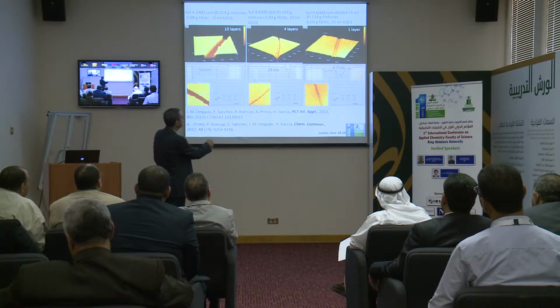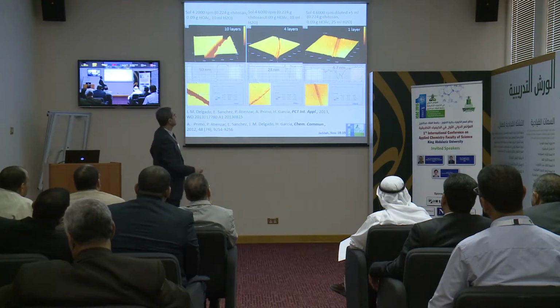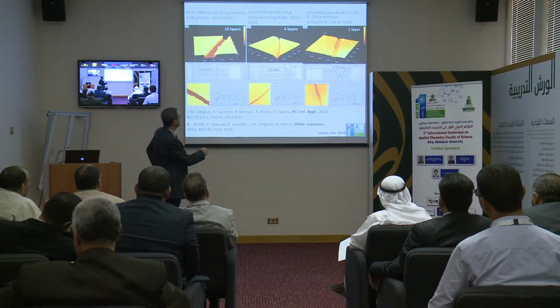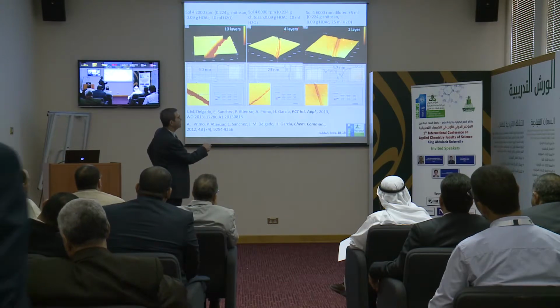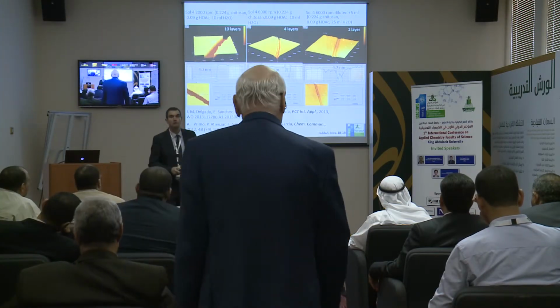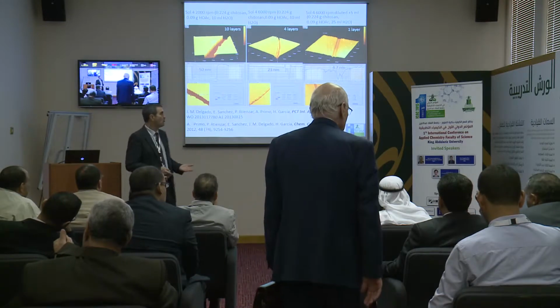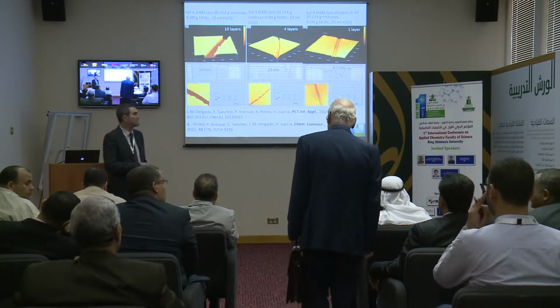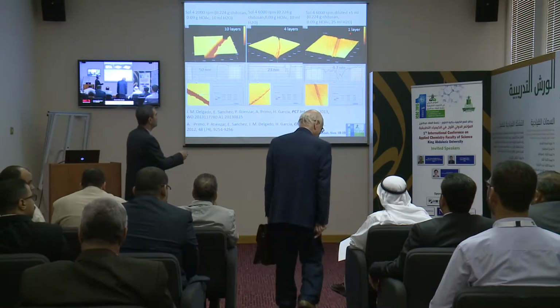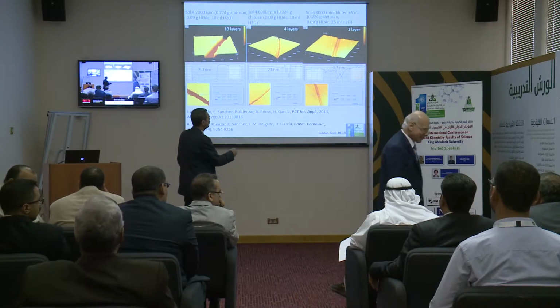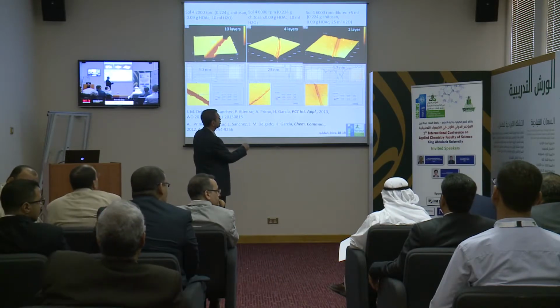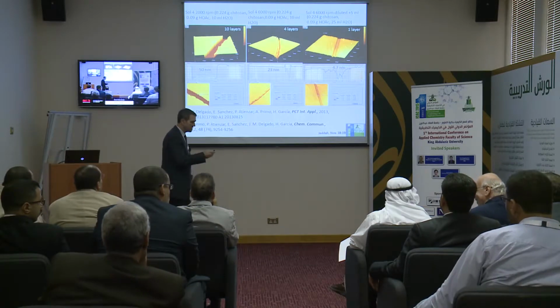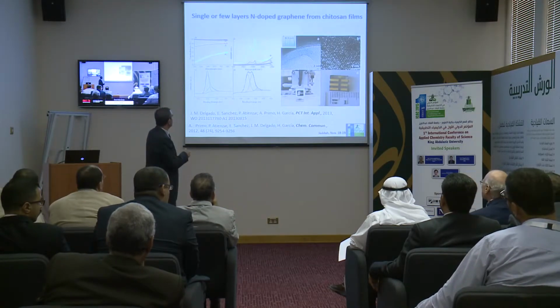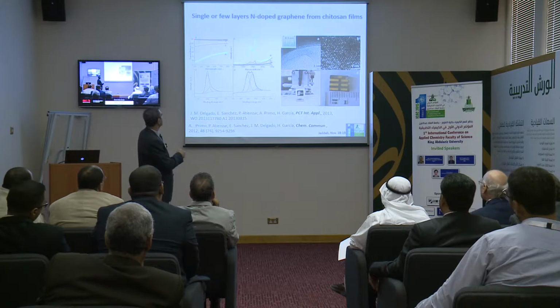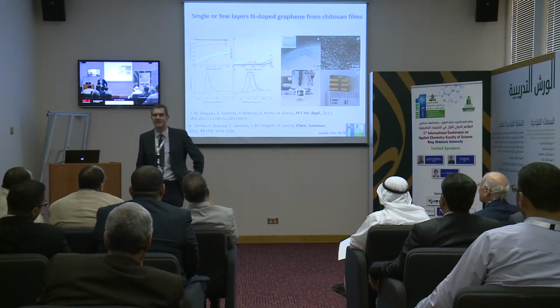Again, very nice, very smooth surface. And when we pyrolyze with this thickness, what we have is 4-layer graphene. So we can control pretty well the thickness of the precursor, and by controlling the thickness, in the end we control how many layers of graphene we form. For instance, in this case, with 4.7 nanometers of the precursor, at the end what we have is single-layer graphene.